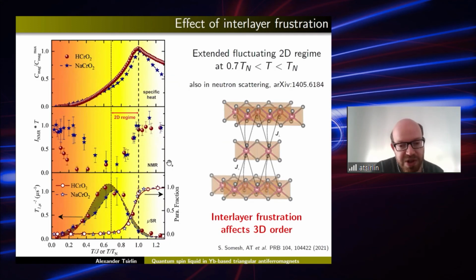And that's what we did in collaboration with Ramesh Nath and Philippe Mendels, studied a couple of these chromate compounds, the hydrogen chromite and sodium chromite. And we saw actually a very unusual behavior, which is also universal across this whole compound family. If you look at the specific heat, then you would think, okay, there is just the standard boring magnetic order in here. But if you start to look locally, for example, at NMR intensity or at the muon spin rotation, then you see that there is a quite extended regime going to around 70% of TN, where the system seems to have the pure two-dimensional spin fluctuations.